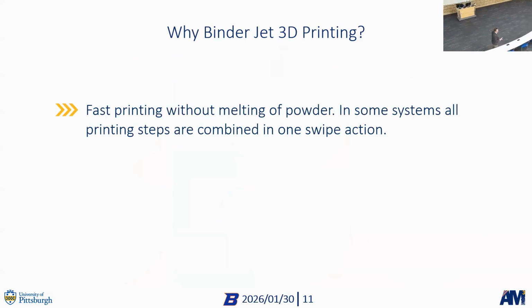If you know laser powder bed fusion, you have like one laser or maybe two lasers. It takes a minute or two for each layer to actually print. Here, modern systems can actually do the entire single layer in one swoop. So you have powder deposition, directly behind it printing, and directly behind it drying, right? So the process is about 100 times to 200 times faster than laser powder bed fusion.